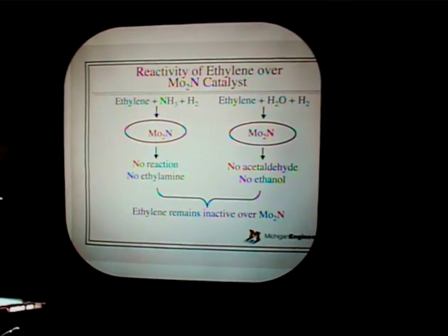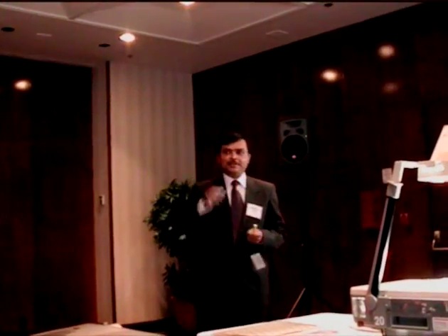Did you try that without hydrogen or water? Yeah, we tried, but the drop in activity was very fast. Probably ethylene is undergoing some polymerization, something like that. Within 2 hours, it almost became zero. So we couldn't take any significant reliable data. Okay, thank you very much.